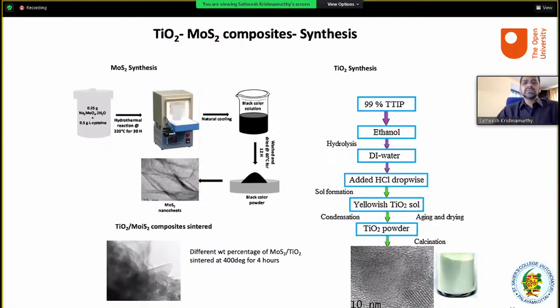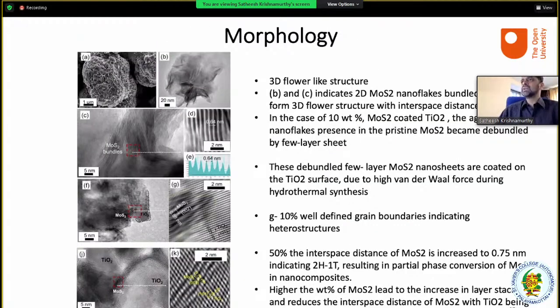So we make this process simple using a chemical treatment, hydrothermal treatment. Hydro is the water, thermal is the heat. So we mix water with it and produce with heat, which makes composites, and from the composites we will get a layer. Look how nicely it forms a layer. It's a very simple method of producing. And then different morphologies from flowers to lines, you can tune accordingly.